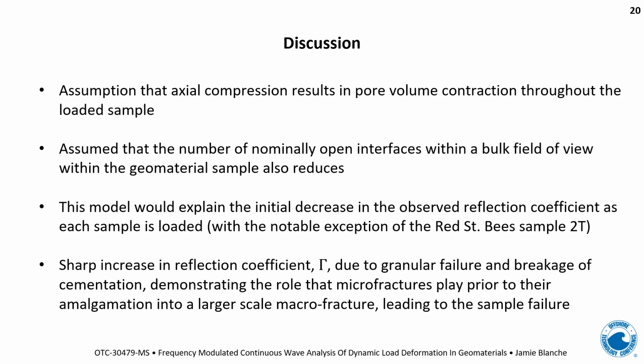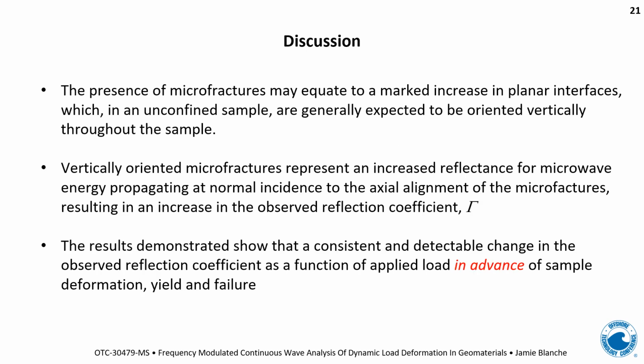So there's a sharp increase in the reflection coefficient due to granular failure and breakage of the cementation between the grains. This demonstrates the role that microfractures play prior to their amalgamation into the larger scale macrofracture, which overall leads to the sample failure. Therefore, we're taking that the presence of microfractures may equate to a marked increase in planar interfaces, which in an unconfined sample are generally expected to be oriented vertically throughout the sample, as previously explained. So vertically oriented microfractures represent an increased reflectance from microwave energy propagating at normal incidence to the axial alignment of these microfractures, resulting in an increase in the observed reflection coefficient.